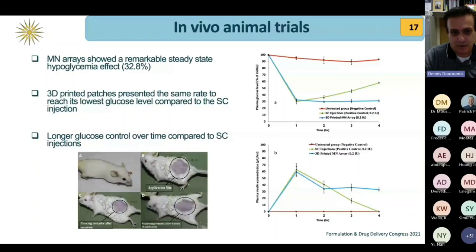insulin in vivo. So what we found was that, again, I'm not going to go in detail, but we found that the duration of plasma insulin by using microneedles was much better. It lasted at least for 4 hours, and the same thing with the glucose levels were reduced for longer period in the blood plasma, but also the insulin levels were much higher. But when we use microneedle administered work, microneedle administered insulin.